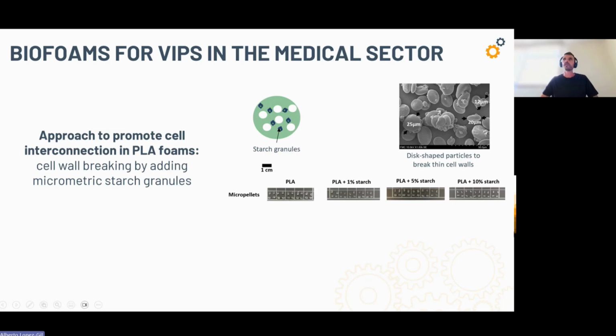So we needed to come up with several approaches to do this. If we wanted to have an open cellular structure using a conventional PLA grade, we came up with the idea of using bio-based particles, in this case micrometric particles, such as native starch. So this is our foam at high densities yet, and the particles, in this case native starch granules, embedded into the solid polymer. As you can see here, this is an SEM micrograph of the native starch. The size is very small.